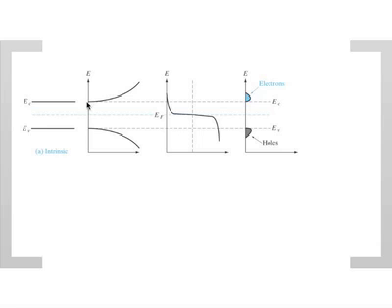So what it's saying here is that the density of states here is that number, whatever that is. Then it increases in a parabolic fashion as you go up. So higher energy has higher density of states, more available energy levels. That is actually an important idea, it turns out. We'll come back to that. And down here, of course, we do the opposite because it's the holes. Energy for the holes increases downwards. Okay, so same thing, but it's relatively symmetric.